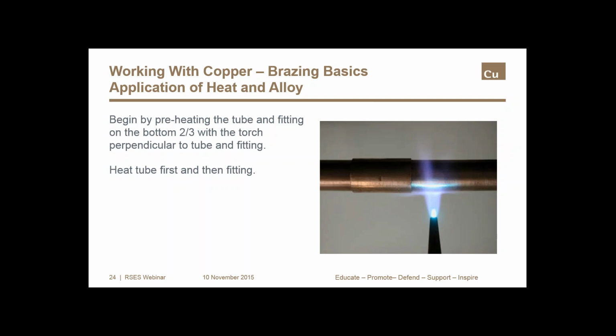So after heating the tube, switch the flame to the fitting at the base of the cup. Sweep the flame from the fitting to the tube to get uniform heating. As a fitting comes up to temperature, start sweeping the flame back and forth along the axis of the joint to maintain heat in all the parts to be joined. Remember to keep the flame moving to avoid damaging the tube or the fitting. If cast fittings are used, exercise caution to avoid excessive heating that might crack the fitting.